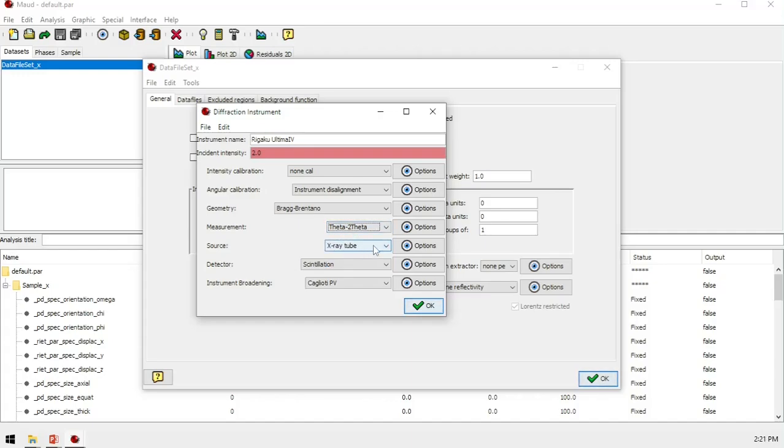And then the X-ray tube is important, because when I was doing the refinement, I found out that there is a K beta which is not completely eliminated, and this is why I also use the standard material to see the wavelength.